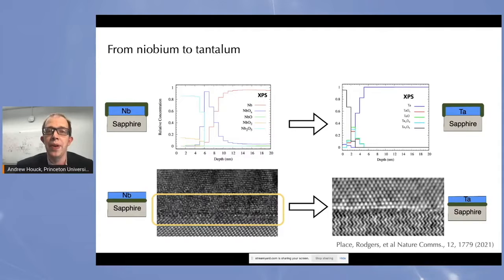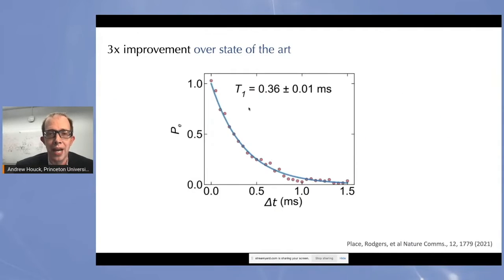When you put this together and actually build quantum devices out of it, how long do things last? It turns out that we can get devices that are up to 360 microseconds here. So over a third of a millisecond, a 3 times improvement over the state of the art. If we do this across many different devices, we can actually see that this improvement is robust. Since we introduced this new material system, we've been able to achieve these kinds of coherence times across many different devices over many iterations. We've exported this process to many other academic groups around the country by teaching them how to grow these films.